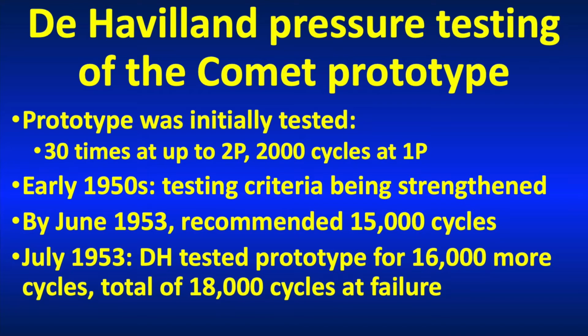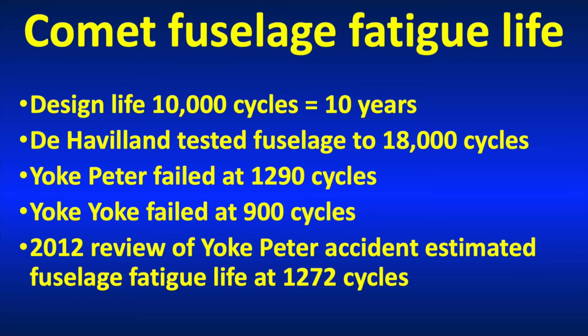So by 1953, people were recommending that aircraft should be tested for 15,000 cycles before they could be certified. So de Havilland took their original prototype and they did 16,000 more pressurisation cycles in it before it failed, for a total of 18,000. So they were very confident, as I said earlier, that this was not going to be a problem, because the aircraft was only designed for a life of 10,000 cycles. But if we look at the Naples aircraft, that failed at 900 flights, so only 1/20th of the life that de Havilland had tested the aircraft to. So there's clearly a significant disconnect there.